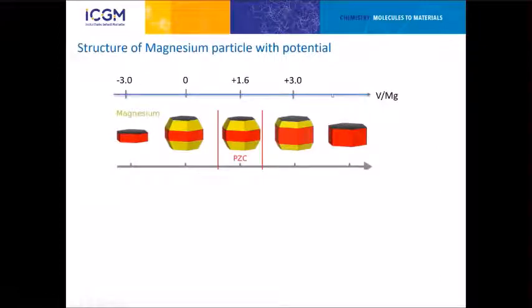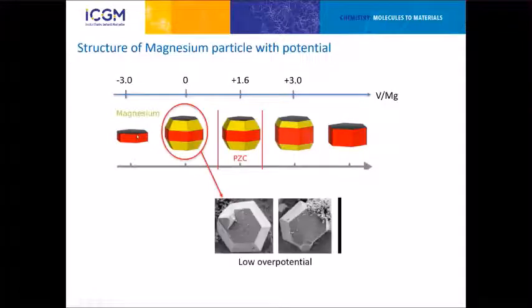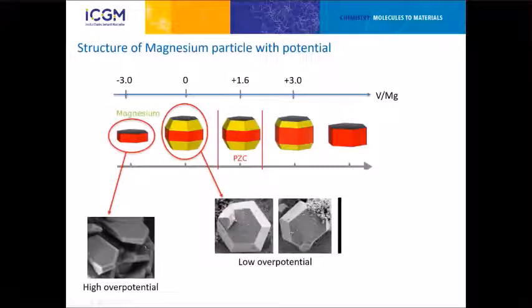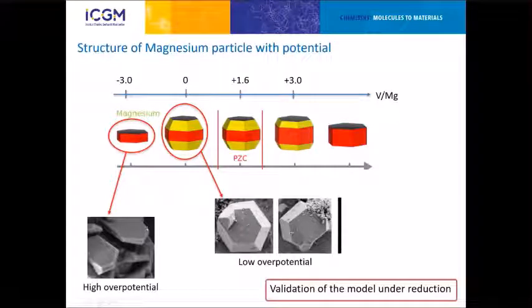So first, we checked that we get the proper energetics for magnesium. So we modeled the magnesium nanoparticles at different potentials. We find that if you do the uncharged surfaces, we get a very high potential relative to magnesium, plus 1.6. So it will be, once again, a metastable system. The structure corresponding to the zero charge will be quite similar. It will be mostly a bulky octahedra. And when you go to very high overpotential, you get some kind of hexagonal platelets, in correspondence with what is found experimentally. So things seem to be fine also for magnesium as for lithium.